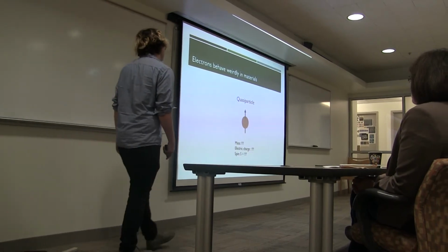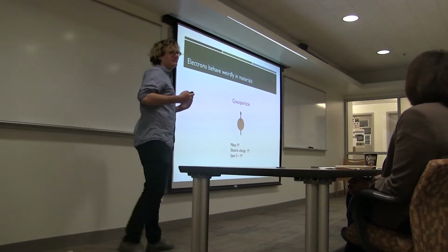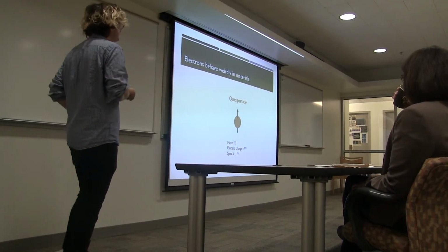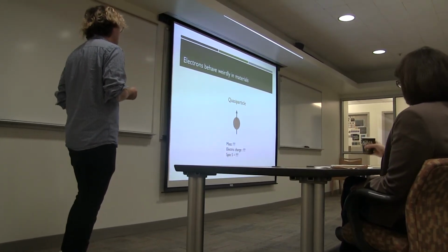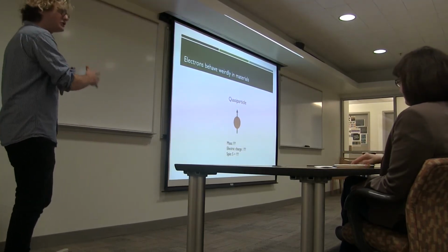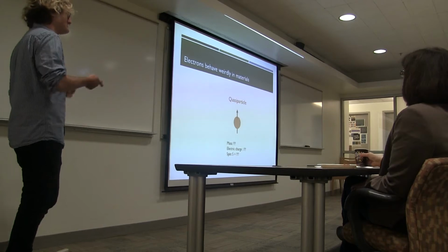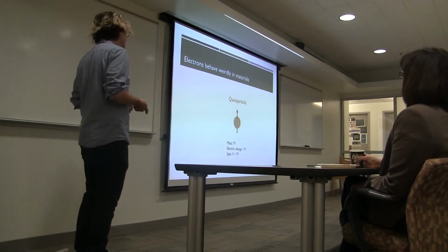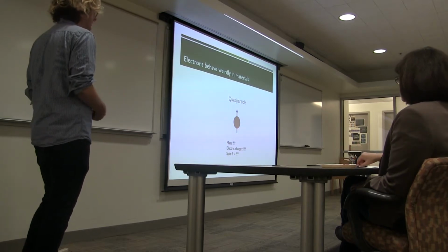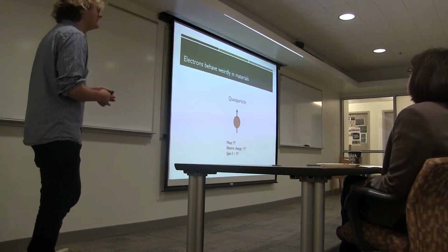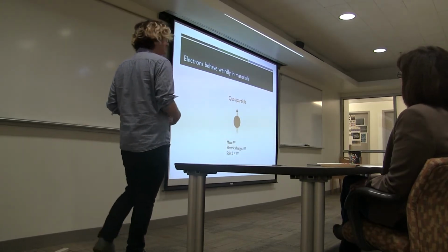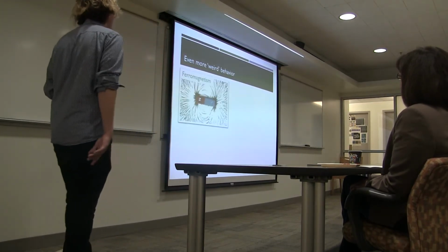And so the question is, what else can we change about this quasi-particle from how electrons normally behave? And it turns out a lot of things. For instance, the mass of the quasi-particle can be anywhere from a small fraction of the bare electron mass to 1,000 times the mass in heavy fermion materials. Also, in some exotic materials in a magnetic field, you can get electric charges which are fractions of the normal electron charge. So there's really exotic stuff that can arise from just putting electrons in a lattice.